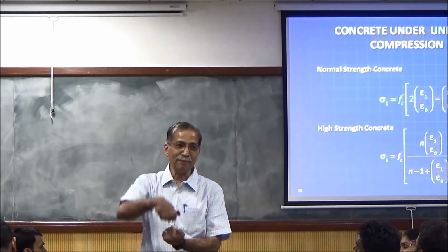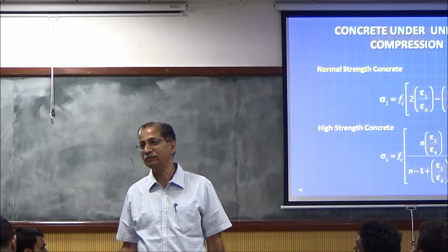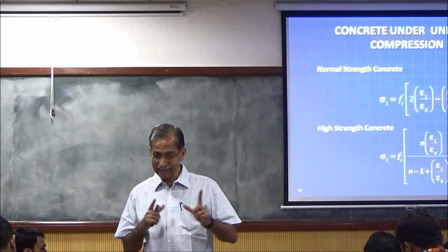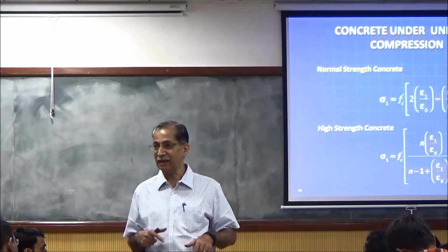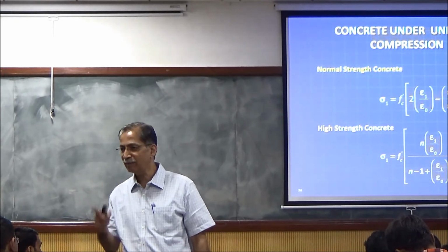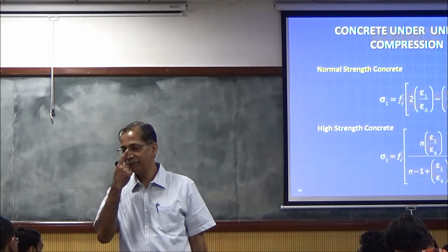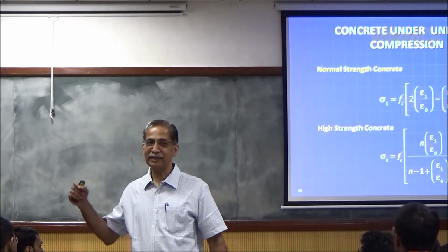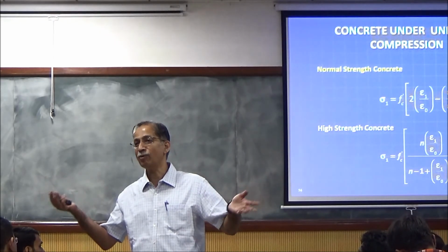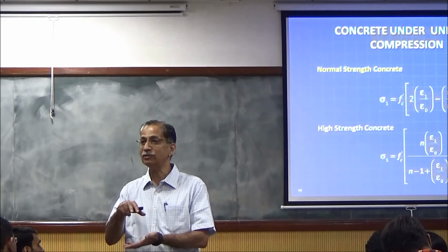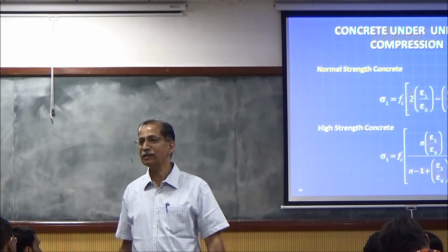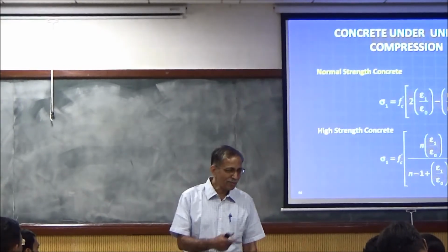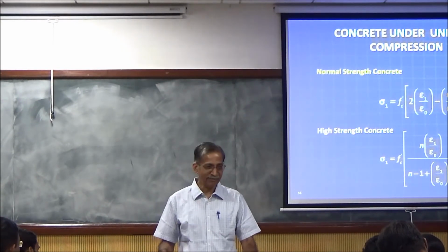Crushing is in compression, cracking is in tension. Got it? Sometimes both happen. But the early signs are cracking, vertical cracks. Any more questions? The crushing point we obtain is the final point in the stress-strain curve. Yes, that's when it gets crushed, after it can't take any more load, once the movements are so large it can't take any more. Got it? Clear? Going very slow, but I think we need to clarify these basics.